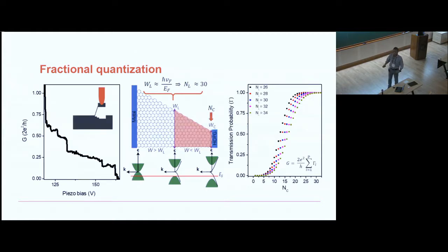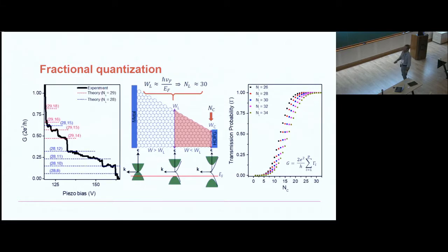And they calculated it. They calculated beautifully. They calculated the resistance of this region alone by keeping this fixed, and calculated how much the resistance would be of this size as I change the number of hexagons on this side by 1. And we then put the results back on our data, and we found that now these states are essentially corroborating with 1 hexagon change on each side.